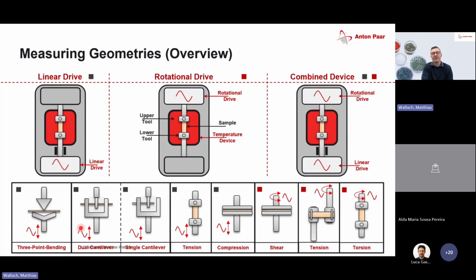In this case, if we have a soft material, we could use a cantilever system where we clamp a sample here, here, and here, and then the sample is stable, and we can just move upwards and downwards and measure the material behavior over temperature. The disadvantage is that the free sample length is very short, so we have a lot of clamping effects in the measurement. So this means transition temperatures are correct, but the moduli that we measure will be too high.